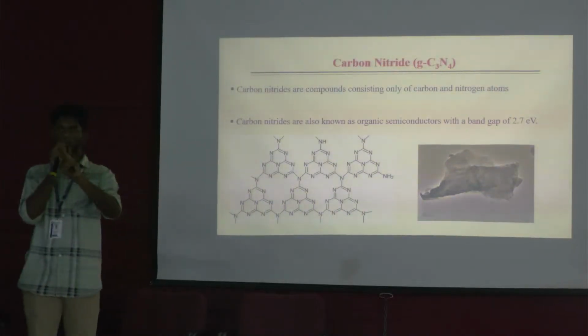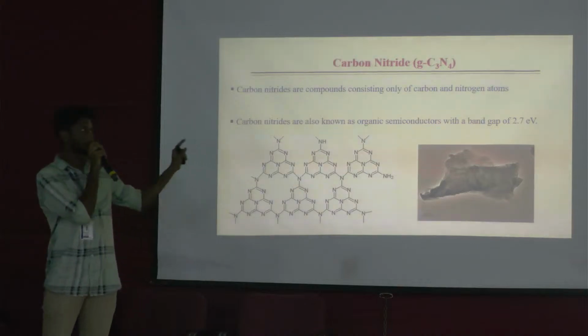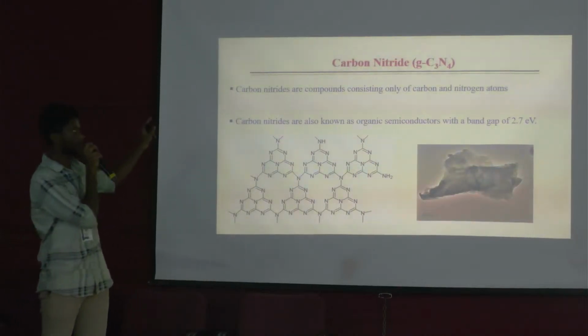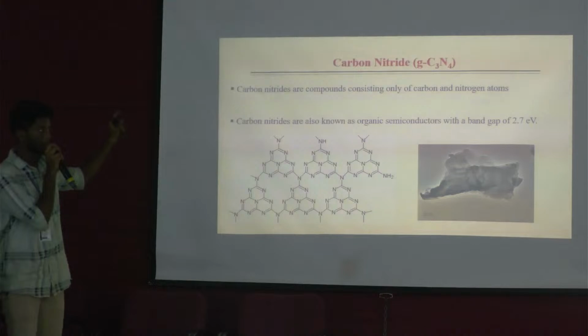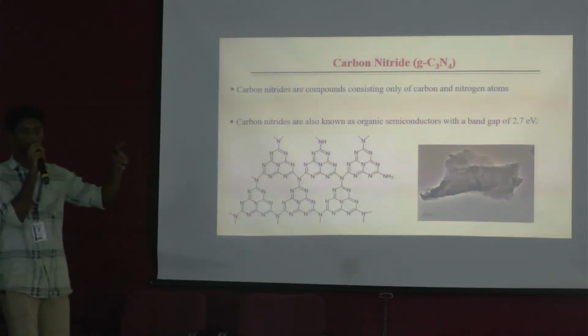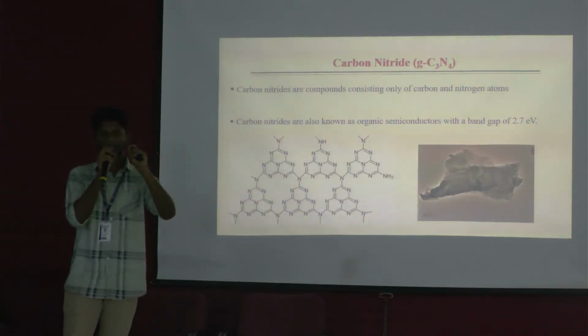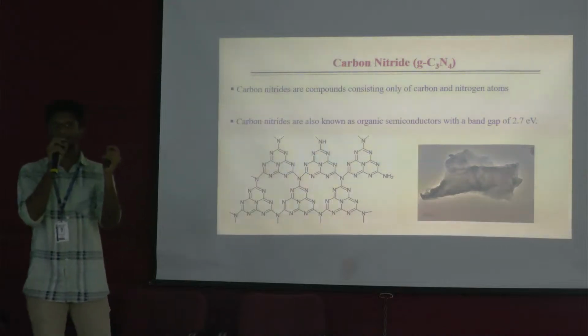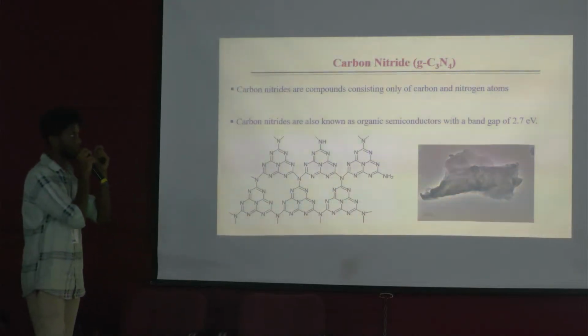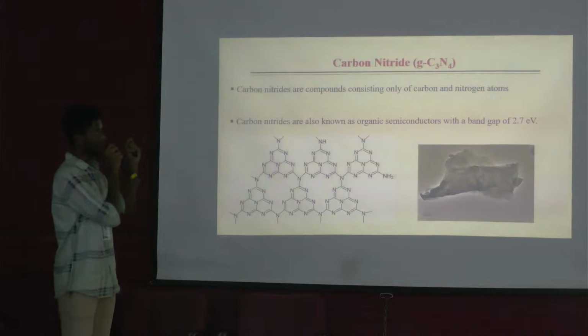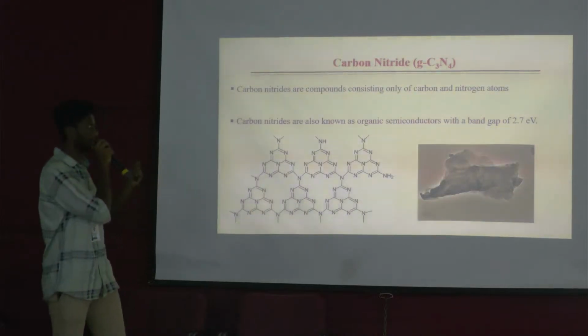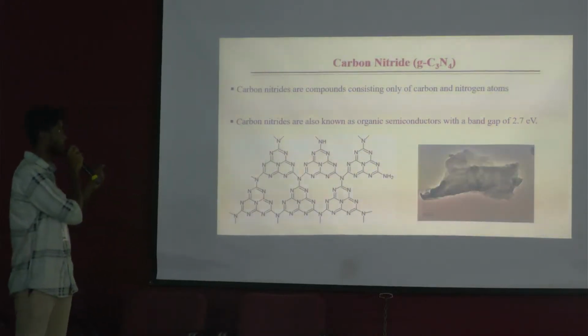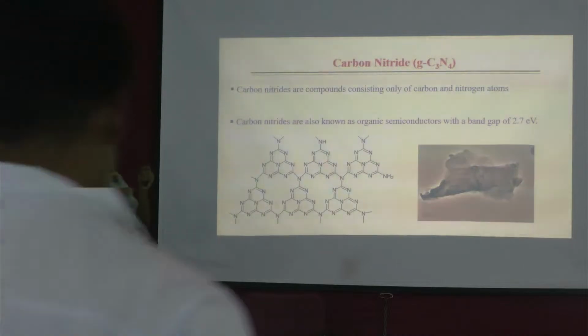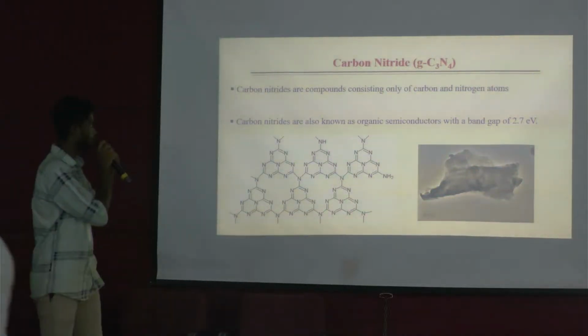Nanocomposite: two compounds exist there. One is nickel oxide and the other is graphitic carbon nitride. Graphitic carbon nitride is made from urea, melamine, nitrogen-containing compounds, which decompose at high temperature and give graphitic carbon nitride, a compound consisting only of carbon and nitrogen atoms.